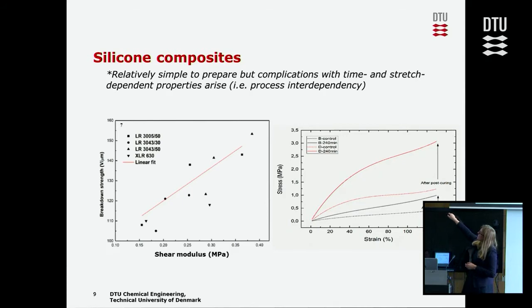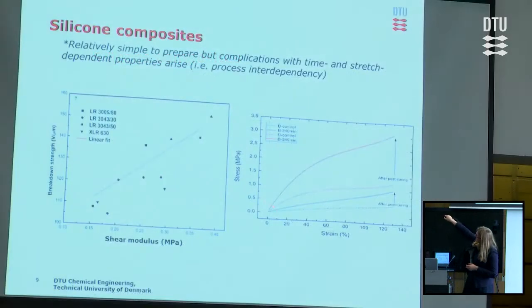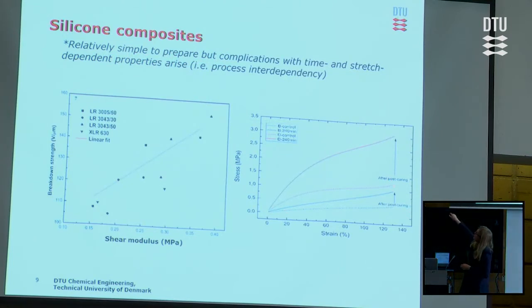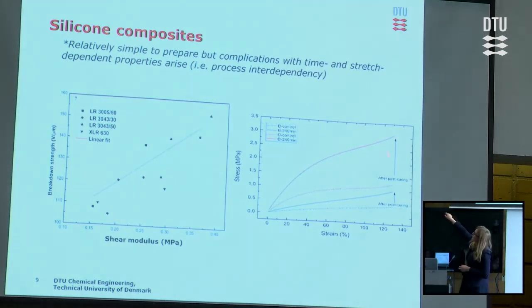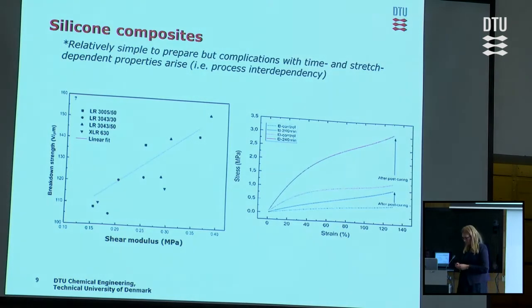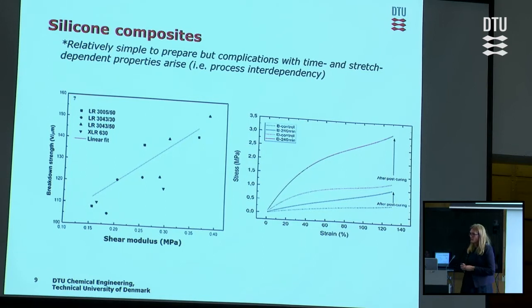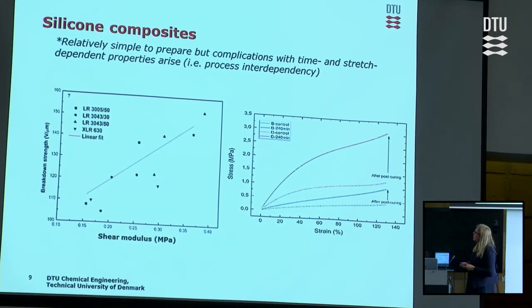Here is just shown, we cure our elastomer, and then we have our stress-strain looking like this. We have a soft and compliant elastomer, and then we remove a few percent of our solvent, and suddenly we have a much stiffer material. So we spent a lot of time figuring out how to remove it efficiently, and how to figure out if we actually removed it.